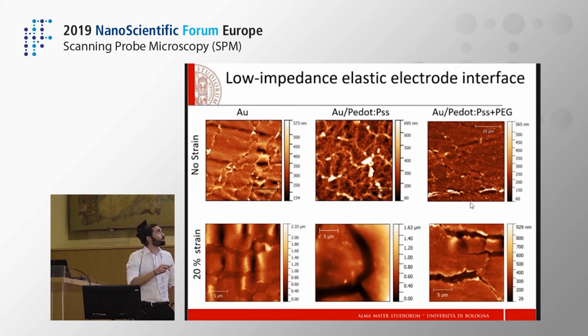But this is not what happens when we have PEDOT on top of gold, and in this case we add additional forces during the crack formation. Thus we have fewer cracks but they are wider, and this basically cuts the conductivity of our electrode. This doesn't happen when we have a plasticizer like PEG, and again, the micro pattern of microcracks is restored.